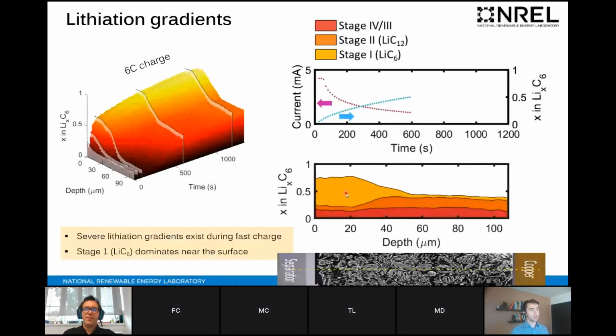And then down here, you can see the contribution of the individual stages. So we've got LiC6, stage 1, LiC12, stage 2. With this experiment, we weren't able to decouple the resolution of the other stages, stage 3 and 4. So we bundled them into kind of one stage, so 3, 4. That's about LiC30 or LiC18. And you can see the mass fractions of those phases as a function of depth and time here.